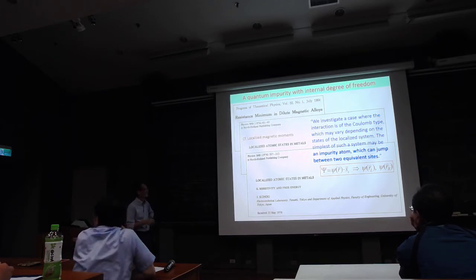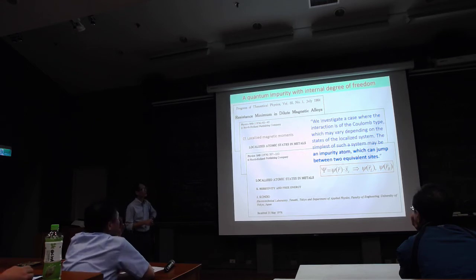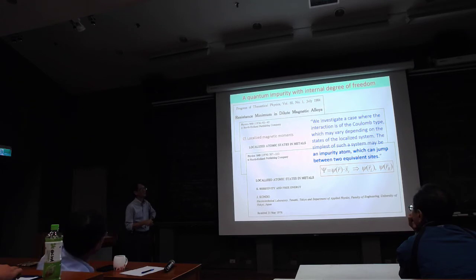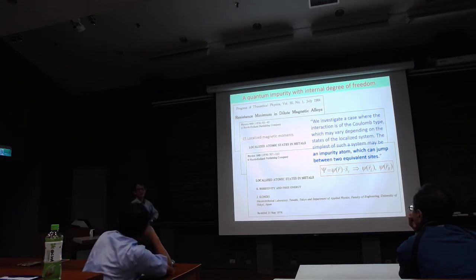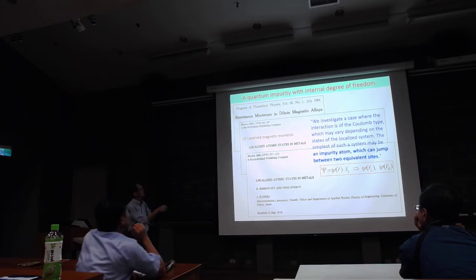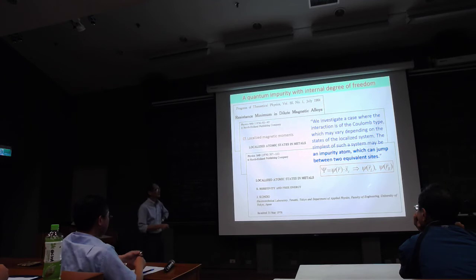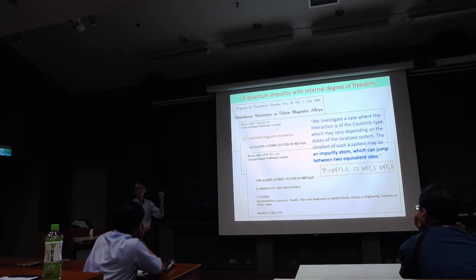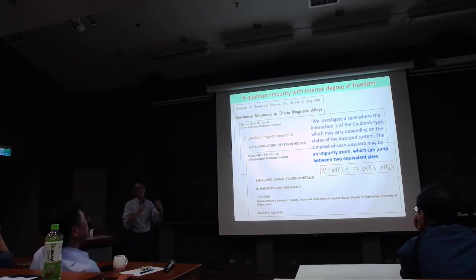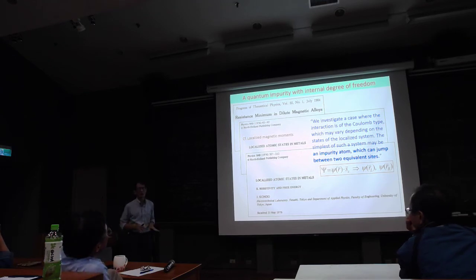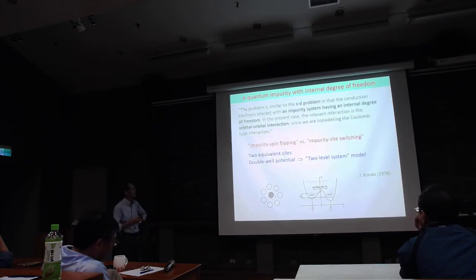Okay. In the original Kondo theory, the conduction electron spin interacts with this local moment. And then 12 years after this original work, he realized that if you have a defect, no moment, no spin, but this defect can sit on the right position or left position, and switch back and forth. And if their energies are degenerate, then one electron coupled with this, interacting with this, can actually also be fully mapped into the original Kondo Hamiltonian, and you will have exactly the same phenomenon. So this is the idea.